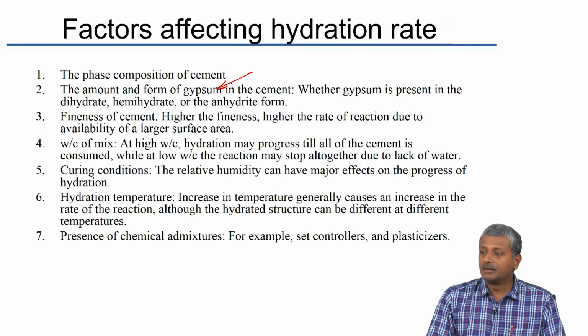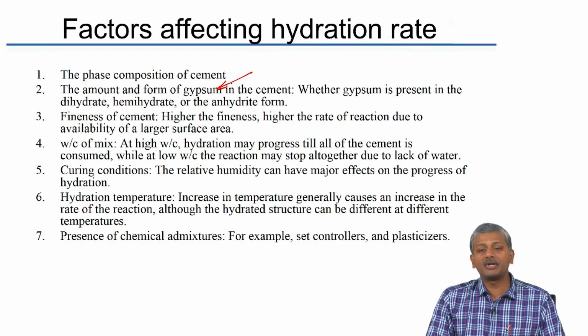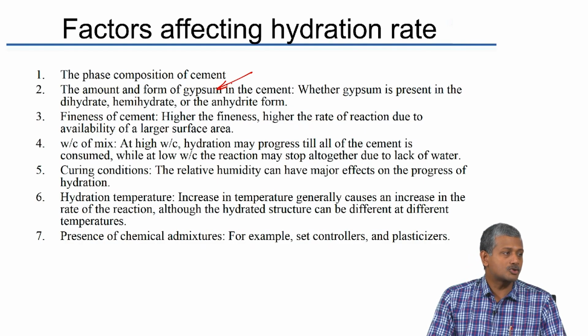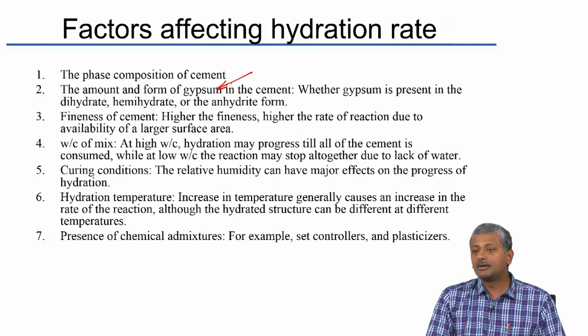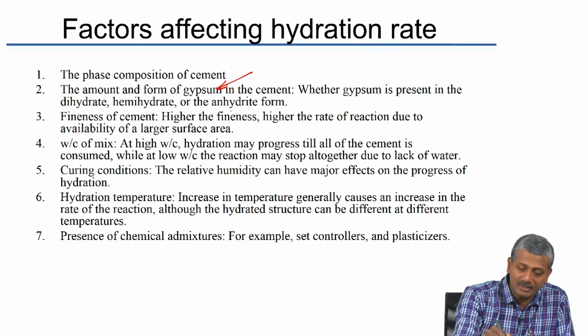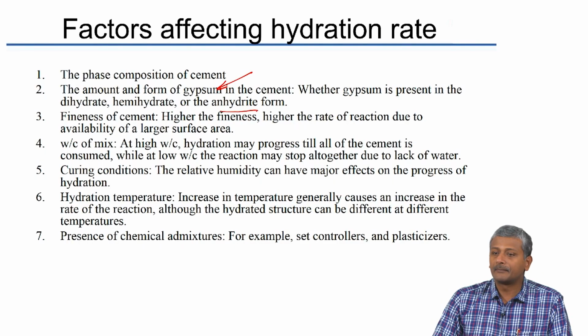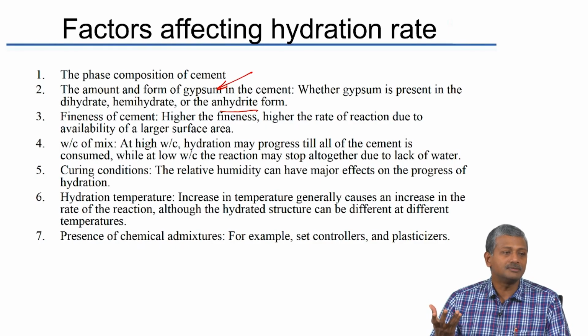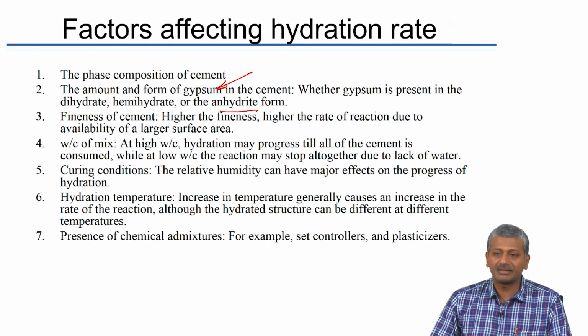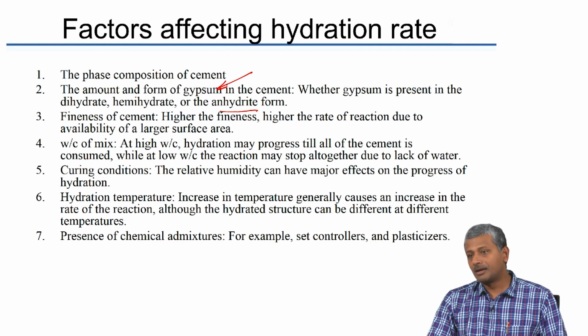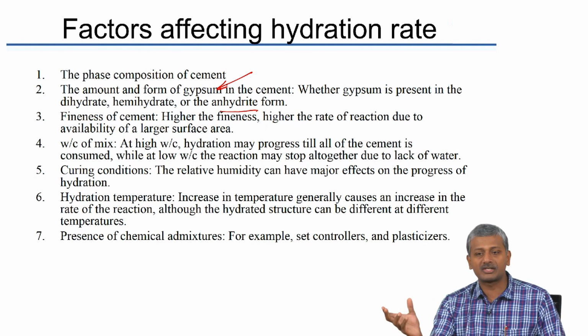Now, interestingly, gypsum can be also obtained from a natural anhydrite. That means calcium sulphate can be also obtained from natural anhydrite. That is a completely different material as opposed to a synthetic anhydrite. What do I mean by synthetic anhydrite? Exactly. You take gypsum and increase the temperature, you lose the water of crystallization, that becomes a synthetic anhydrite. A natural anhydrite is naturally available calcium sulphate.